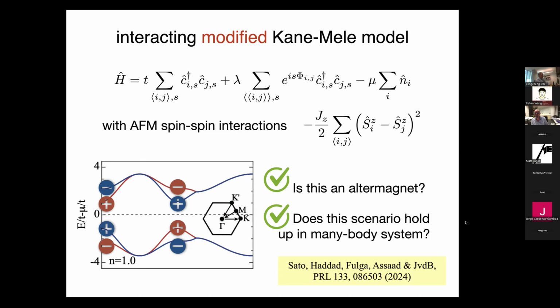Since the anomalous Hall effect depends on the sublattice magnetization, if you change the domain, the sublattice magnetization also changes direction. So if you have two domains present in equal amounts, the anomalous Hall effects tend to cancel. That's something you want to get rid of in the first place. And I would say doping in general, as long as it doesn't change the magnetic ordering and the symmetry of the magnetic ordering, does not play a role in itself.